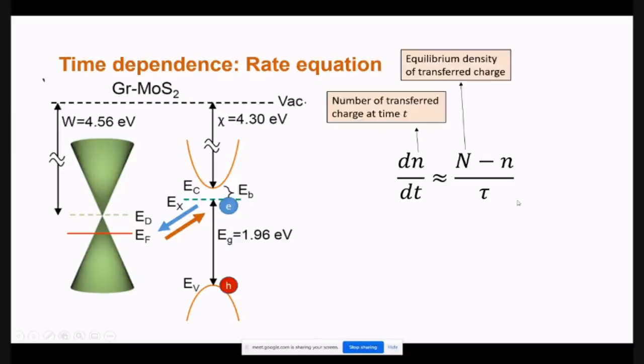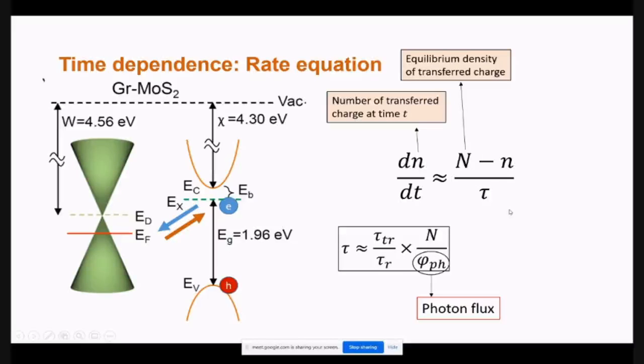And you can form a rate equation like this, in which this effective time of charge transfer is really given by a balance of the charge transfer rate, tau TR, which is the rate from chalcogen to graphene, and tau return, tau R, which is the recovery time of the exciton within the chalcogen layer. So if you put these things together, you get a simple first order differential equation after some approximation, which gives you an exponential relaxation. Okay, and that gives us a very correct order of magnitude of the expected time scale as well.